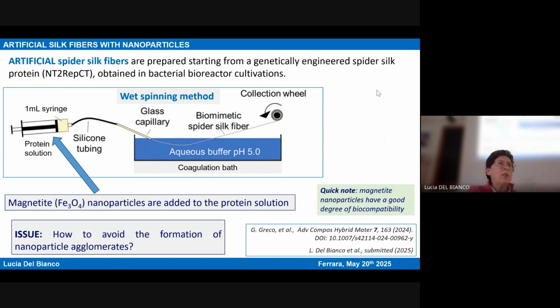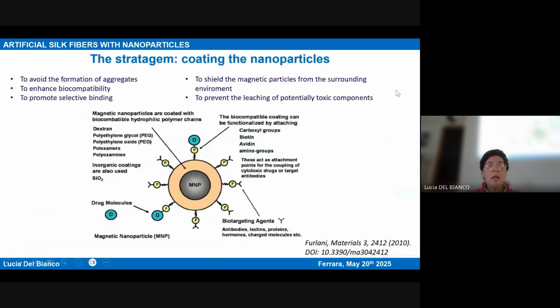And not just because they are magnetic and therefore they can interact by dipolar interaction, but all the nanoparticles are strongly interacting and tend to form agglomerates. I mean, even non-magnetic, and mainly due to van der Waals interaction, so electrostatic interaction at the end of the story. And so how to avoid the formation of nanoparticle agglomerates? The idea is the same, using the same stratagem that people use to avoid that any kind of nanoparticle forms agglomerates, namely coating the nanoparticle, which means growing around your magnetic nanoparticle a different phase, a coating of a different phase, obviously non-magnetic, and in general it is an inorganic coating.